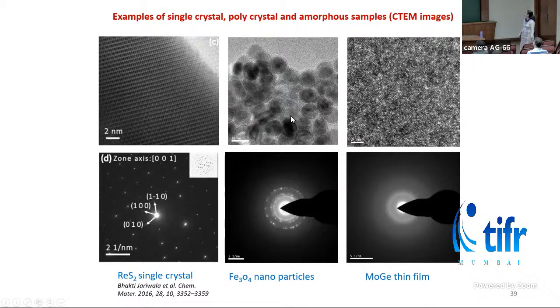particular planes. This is an example of iron oxide nanoparticles, which are 20 nanometers in size, and these are oriented randomly. And if we take a diffraction pattern of this whole region, we can get a ring diffraction pattern, because there is no particular orientation. This is an image of a thin film, which is amorphous in nature. So amorphous samples will show diffraction patterns which are a little diffused.